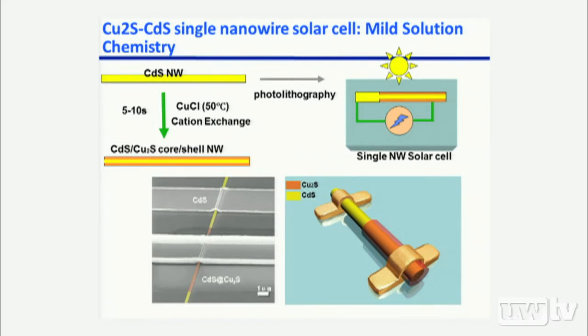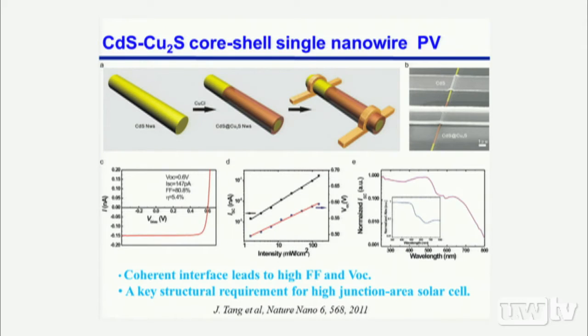Through this process, you can fabricate these core shell nanowires into a solar cell and start to measure their performance. Now, if you look at the performance of these nanostructures, I'm not going to spend too much time on those; the two plots on the right, mainly focus on this IV plot here. One of the features you may notice is that the IV looks very rectangular in shape. And this shape is telling you that the fill factor of this particular device is quite amazing. We are looking at 0.8.